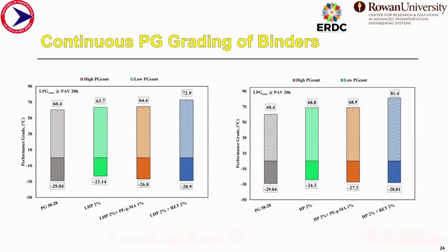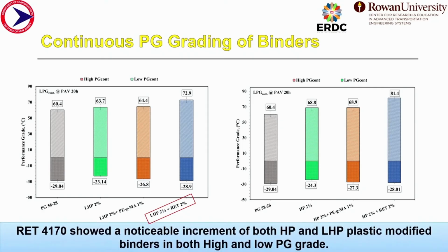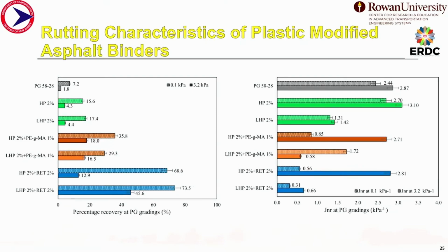But apparently, when we add the stabilizers like the maleic anhydride and RET, we can clearly see that these are improving both the high and low PG grade, where LHP2 with RET is maintaining the low PG grade almost similar to the control binder, which is PG5828, and also improving the high PG grade. So from here, we can see RET is performing better than maleic anhydride in terms of both HP and LHP plastic for high and low PG grade.